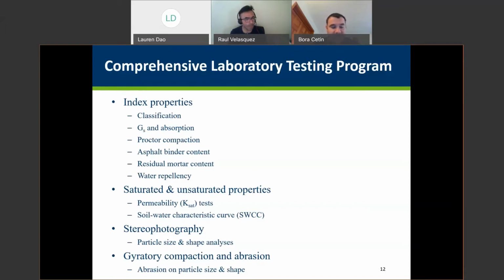And we tried to get the angularity measurements of these materials, whether they change within the materials, with stereophotography, and also tried to determine the particle size distribution and the shape characteristics of these materials. We won't talk much about it in this presentation, but I can tell you that the angularity of all materials was very similar to each other. And then one of the main things is the gyratory compaction and abrasion test, which is very crucial, and we have the data to show that even though the original gradation of the coarse RCA was very coarse material, as you will see in the next slide, after compaction that gradation changes. So you may not want to apply the 100% or 95% compaction degree on some of the coarse RCAs because it may cause a significant gradation change. And if you come to the next slide, please, Raul.